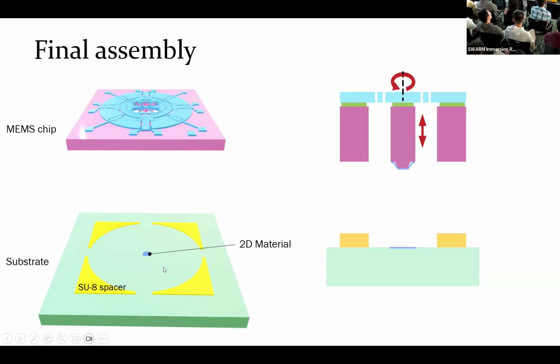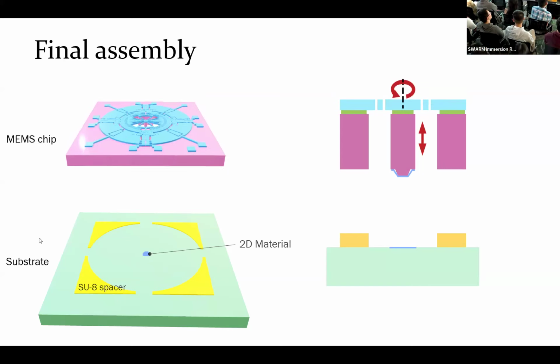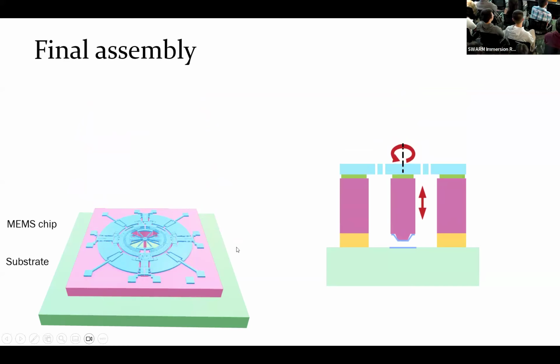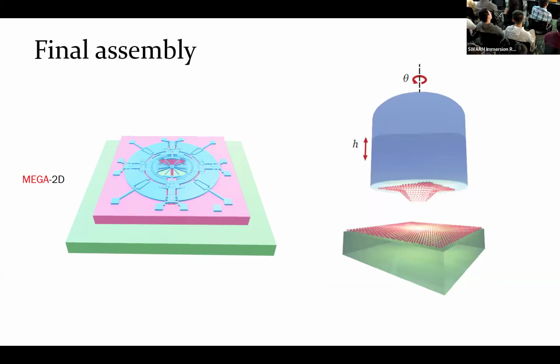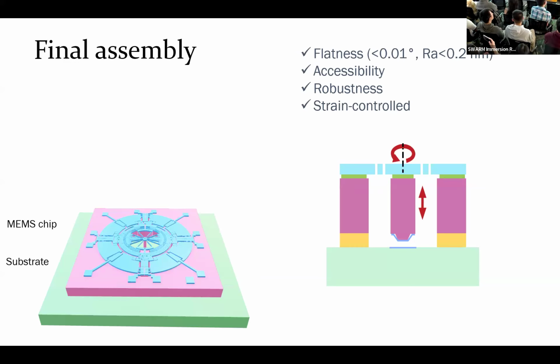basically a glass wafer. And then we put these two chips together and bond them by an SU8 spacer. And now if you drive the device layer of the MEMS device up or down, or rotate it on the axis, then you're basically changing the distance and the twist angle between the 2D materials. Effectively you have a device. If you zoom into the tip, it will be something like that. So one 2D material is tented, the other one is flat, and then you can change their spacing and the twist angle as well. The benefit of this device is that firstly, by design, it is very flat.